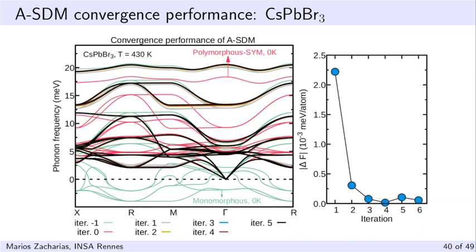And so how big are your supercells typically? Based on my experience for anharmonicity, I use a 2×2×2 supercell for cesium-lead bromide, right? So this is quite efficient to capture the anharmonicity in this system because it's a very small supercell size. But for the electron-phonon coupling, you need to start, let's say, from a 3×3×3 supercell at least, and need to gradually increase your supercell size to obtain convergence.